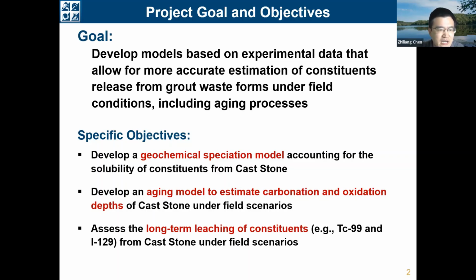Specifically, we have three different objectives. The first is to develop a geochemical speciation model to account for the solubility of the constituents in the pores of the cast stone. Then, to develop an aging model to estimate the oxidation and carbonation depths along with the aging times of the cast stone under field conditions. And finally, by combining the geochemical speciation model and the aging model, we will further develop a reactive mass transfer model to assess the long-term leaching of the constituents.